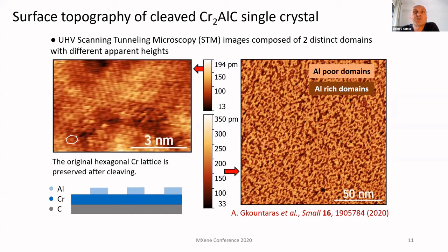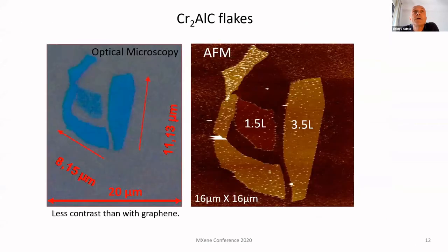Due to the large contribution of the chromium d orbitals to the density of states at the Fermi level, the chromium-rich regions appear closer to the tip, so they are brighter, whereas aluminum disordered or aluminum oxygen clusters appear farther away with a darker color. We may notice that when we cleave a crystal, the aluminum atoms seem to be equally scattered on each of the 2 cleaved surfaces. Now let us have a look at transferred flakes